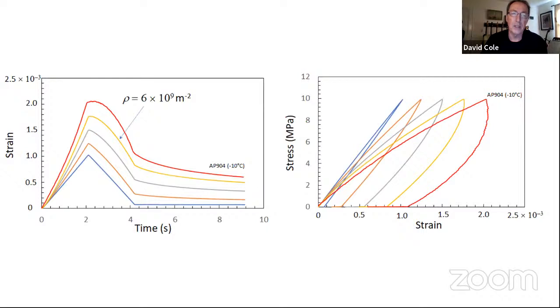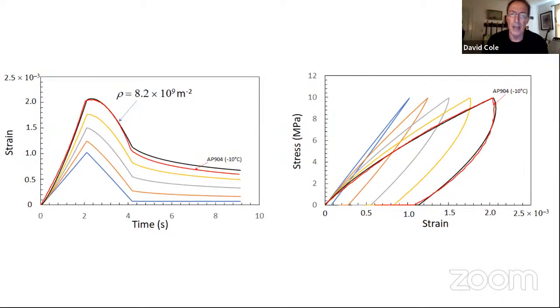Let's go to 6. And we can see now with a high enough dislocation density, we're actually acquiring the shape of the response curve that we're after. And it turns out 8.2×10⁹ is pretty much the magic dislocation density that is reproducing the experimental observation actually quite well. It's a little bit off on the tail, but in general, it's capturing the basic sense of that time delayed behavior.